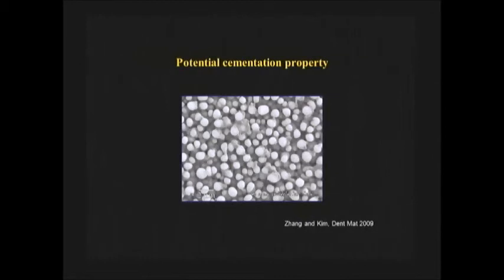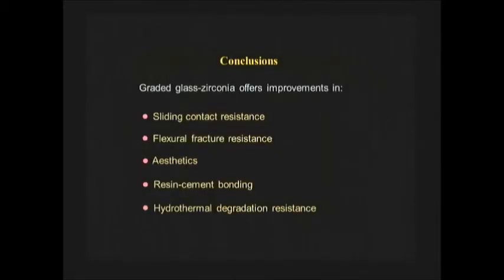And finally, we can etch the integral surface, and then you have a mixture glass-zirconia surface, but it's a three-dimensional rough structure. We can silanize it and cement, and also, without etching it, we can put alumina on it. We can facilitate cementation. And finally, just a conclusion slide, to show you that by grading the surface, by proper design of the surface, we are able to improve the sliding contact damage resistance, flexural damage resistance, and also now provide options for shades, resin bonding, as well as what we're going to test now, the hydrothermal degradation resistance.